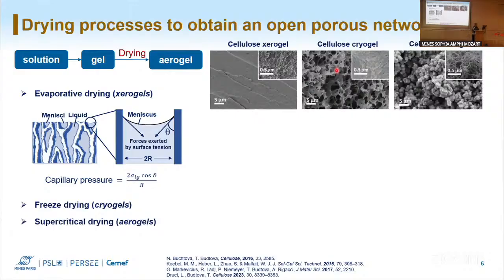And in this case, we eliminate the capillary stresses in our structure, and we can obtain a very fine nanostructure network. And we can see here in this picture that we have very small pores and a very nice structure with fine walls.